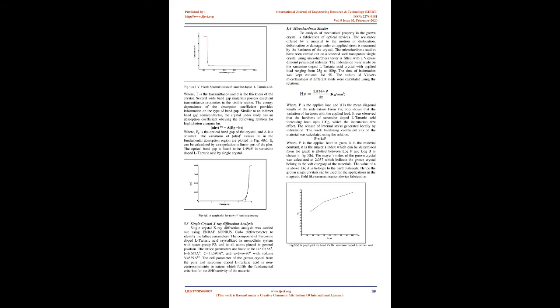Vickers diamond pyramidal indenter. The indentations were made on the sarcosine-doped L-tartaric acid crystal with applied load ranging from 25 grams to 100 grams. The time of indentation was kept constant for five seconds. The values of Vickers microhardness at different loads were calculated using the relation, in kg/mm², where P is the applied load and D is the mean diagonal length of the indentation. Fig 5a shows the variation of hardness with the applied load.